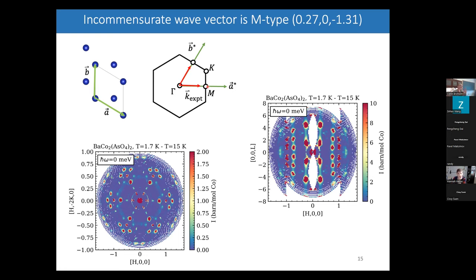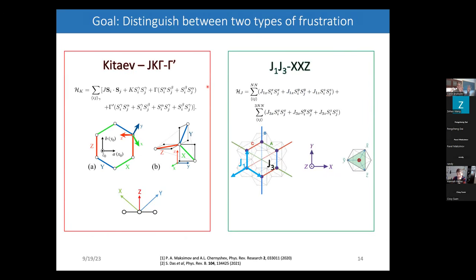In this work, the parameter space is fairly large for interactions. So what we've been able to do, and you'll see that even then it's fairly involved, is that if we specifically focus on these two models, then we're able to exclude the left one, the one in the red box. The J1, J3 model gives a fairly good description of all of the physical properties that we measured.